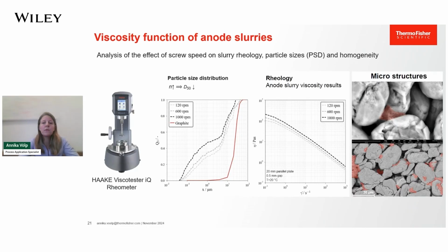Another example shows the effect of screw speed on the particle size distribution and rheology of an anode paste mixed in a twin screw extruder. The left graph shows that with increasing screw speed, a fraction in the size distribution is shifted to a smaller particle size in the anode slurries.